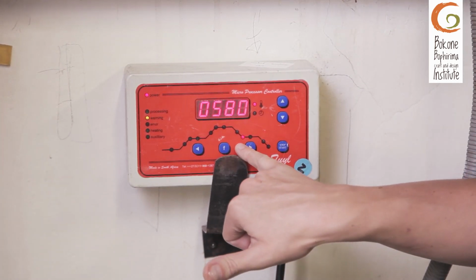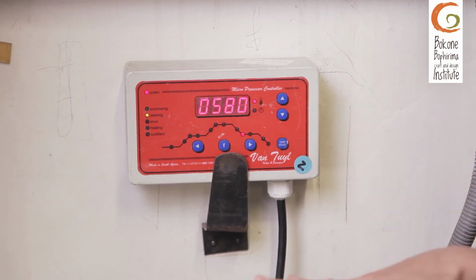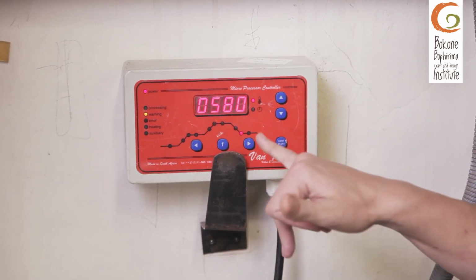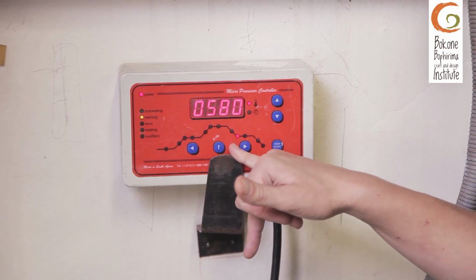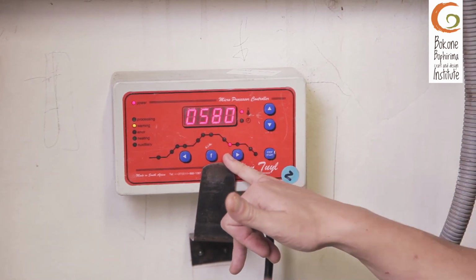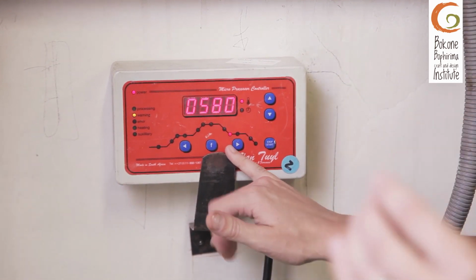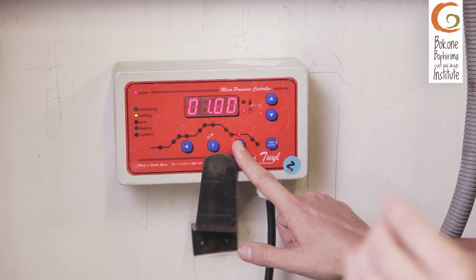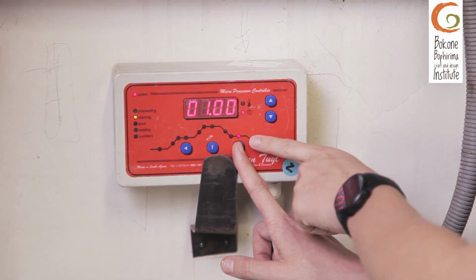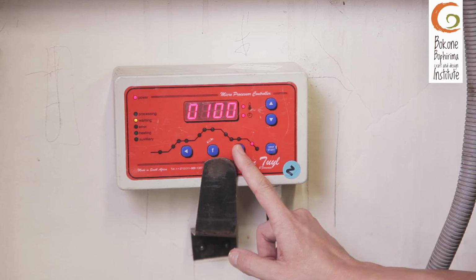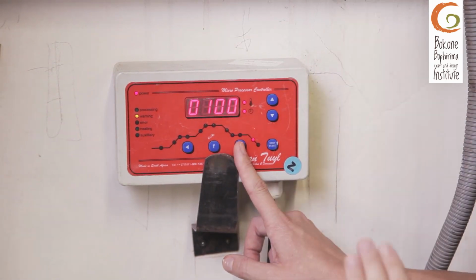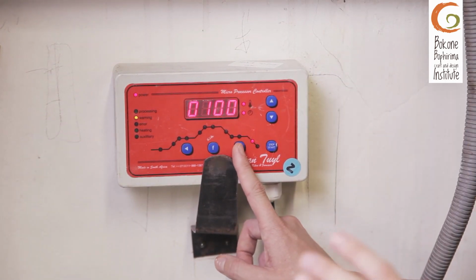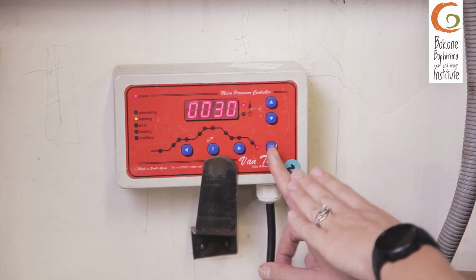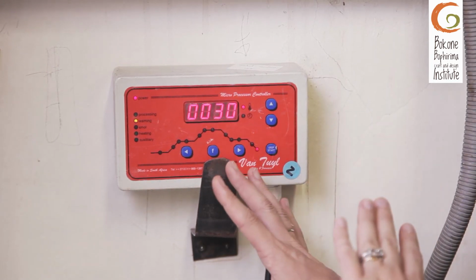And then we'll go down to a temperature we normally want to hold our glass, and then from this process we talk about annealing. So we want our glass to go down slowly, so that it doesn't crack. Again, we can have a delay of temperature, and then we can go down with our annealing as slowly as possible, depending obviously on the thickness of the glass, until normally room temperature or 30 degrees, where we are able to open up the kiln.